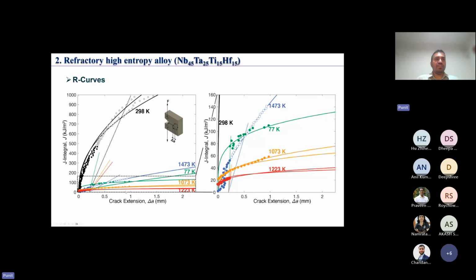And if you look at these other temperatures, you can see a rising R curve at all temperatures. Even at cryogenic temperature, usually all refractory materials have a ductile to brittle transition temperature above room temperature. But in this material, you can see that it's still showing a rising R curve at cryogenic temperature. So it was really interesting to see that we have not actually reached a ductile to brittle transition temperature of this material even at 77 Kelvin.